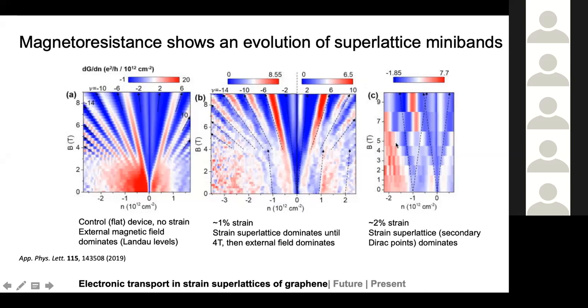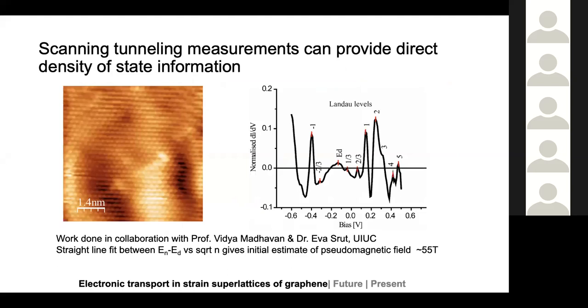So these additional superlattice effects show up even in the magnetoresistance. We also collaborate with a group who do scanning tunneling measurements, and scanning tunneling measurements can give you local information of the band structure in any region of graphene. I find this image to be really pretty. I think it's a Fourier transformed image, but you can actually see each of the graphene atoms over here,